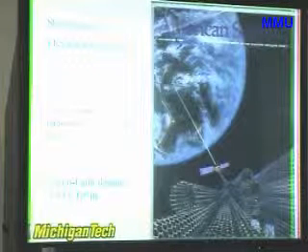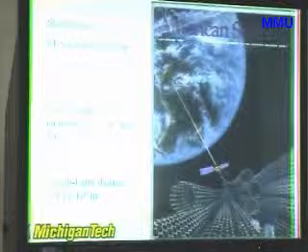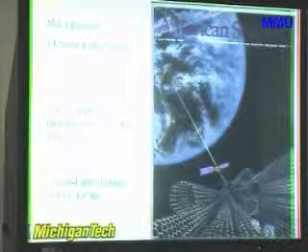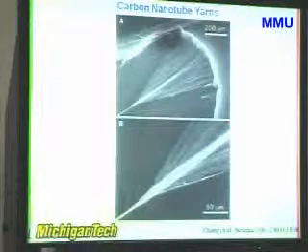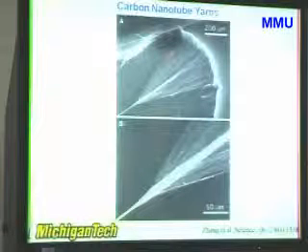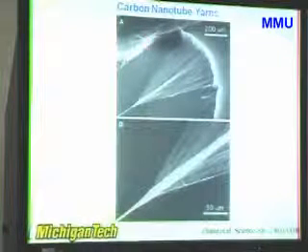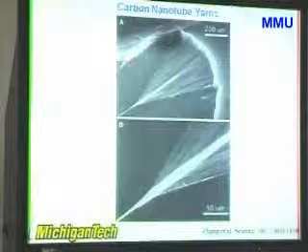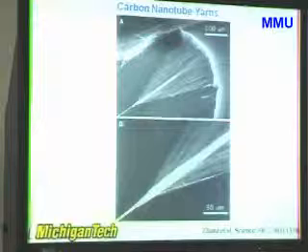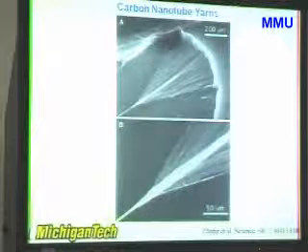But can we grow carbon nanotubes this long? The length is 10 to the power 8 meters. And the world record nanotube so far is 1 centimeter. So this is your assignment, not mine. It's still hard for me. So far we can only grow nanotubes to a few hundred microns mostly, and maximum 1 centimeter. And these are the so-called vertically aligned tubes, which means all the nanotubes are standing vertically aligned, like a carpet.